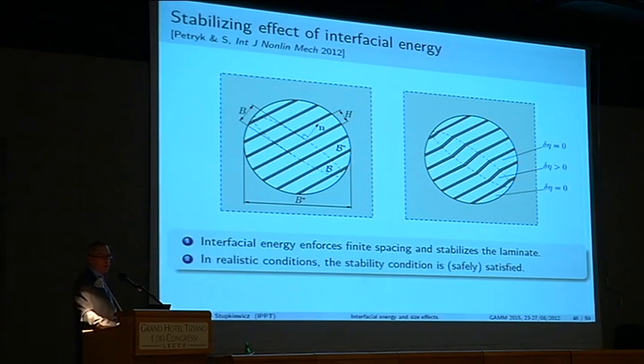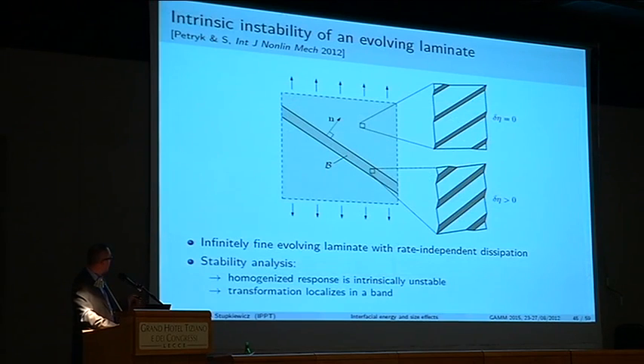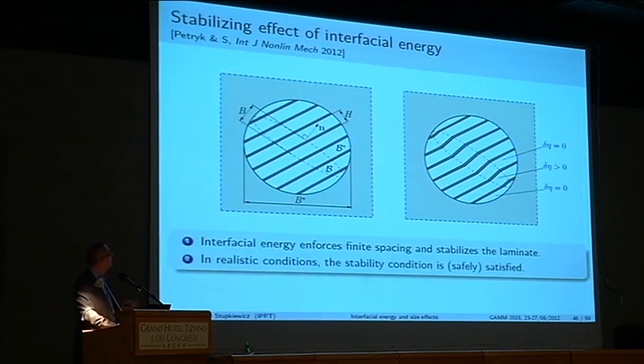Luckily, we have interfacial energy. The basic assumption here was that the microstructure was infinitely fine. But I have never seen an infinitely fine microstructure, I believe no one has seen. So the actual microstructures are not infinitely fine. And it's good news for us, because if we have a finite microstructure with some finite characteristic length, then if you consider the kind of localization mode shown here, we apply here Eshelby's inclusion concept and so on. I don't elaborate much about it.